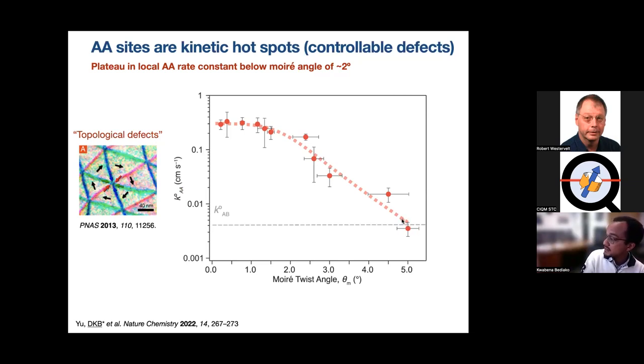And the rates at these AA sites actually show an increase and then they plateau. All right. So even as you go below 1.5 degrees or so, you don't see any change in the rate of chemistry per unit area at an AA site, even though the global Moiré twist has changed. All right. And in that sense, these AA sites are acting as defects, right? Remember, I mentioned how defects enhance electrochemistry, but these defects are controllable in a sense by the twist angle.